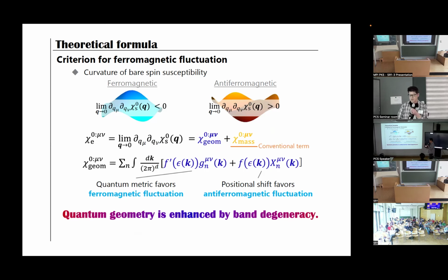Consistent with our naive expectations, we can see the quantum metric here, in the first term of the quantum geometric corrections. We can say that this quantum metric term always favors the ferromagnetic spin fluctuation because this term must be negative. On the other hand, we also have a second term here, which is related to the positional shift of Bloch electrons under the electric field. So we call this term the positional shift term. Unfortunately, this term always favors the anti-ferromagnetic fluctuations. Therefore, the quantum geometric correction to this spin fluctuation is determined by the competition of these two terms.